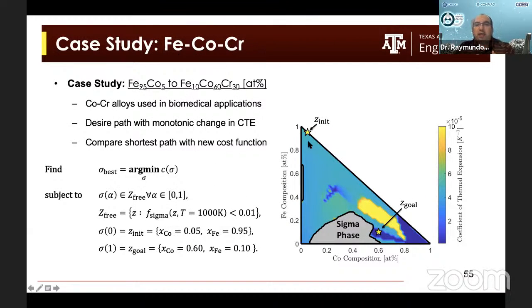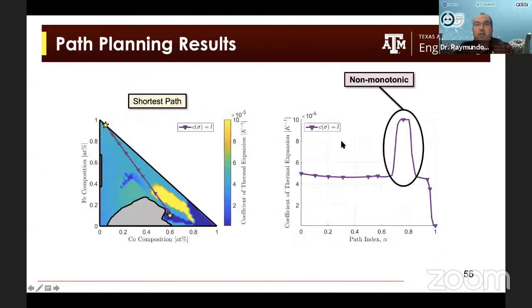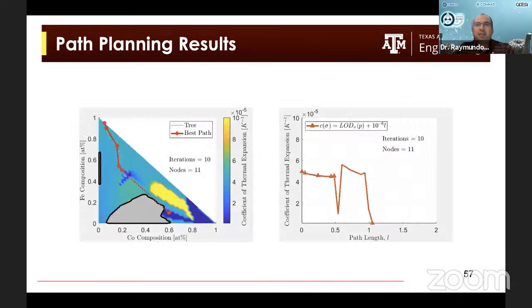And the question was, can we actually find a path between this initial point and this goal point, minimizing the obstacles, so avoiding the sigma phase, and at the same time minimizing, or making the change in thermal expansion coefficient monotonic. Okay, so when we find the shortest path that avoids the sigma phase, this is what we get. We have a non-monotonic change in the thermal expansion coefficient, and this change could lead to dramatic changes in thermal strengths, and that can result in cracking of the part.